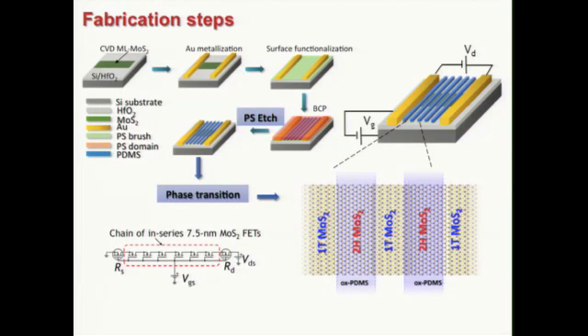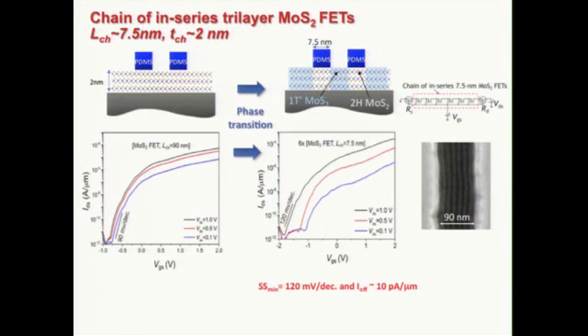That converts the MoS2 channel to a series of metallic and semiconducting regions in series. So actually we have a chain of transistors now, which are in series. The semiconducting parts are the channel, and the metallic parts in between are the interconnects. So here's an example. I have a 2 nanometer thick channel, a tri-layer exfoliated MoS2. And we have 6 lines, so 6 transistors in series. This is before and then after the phase transition.